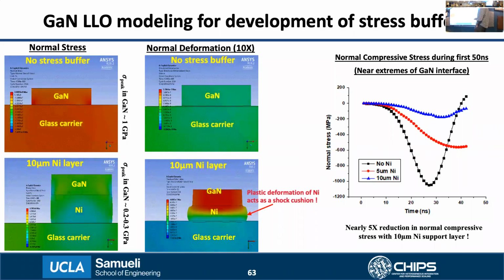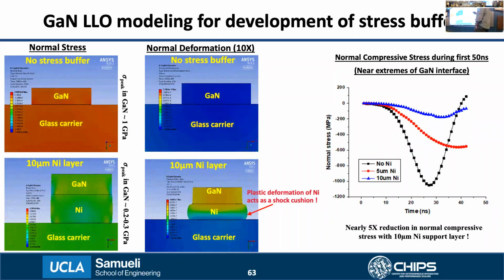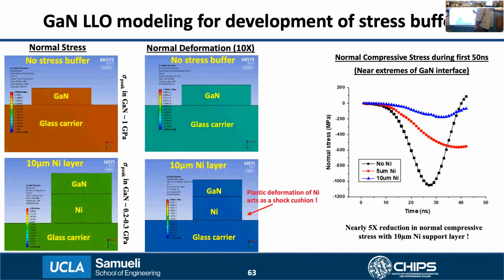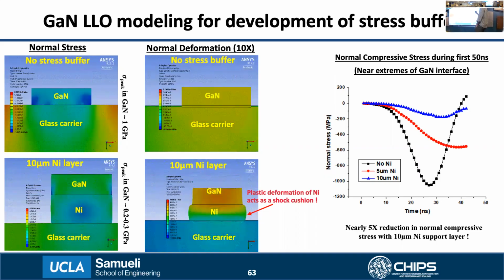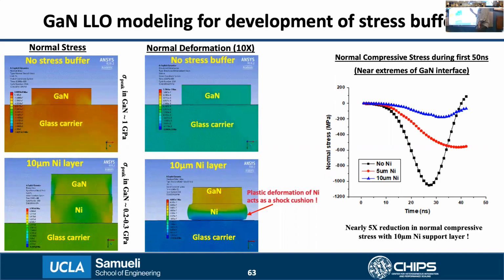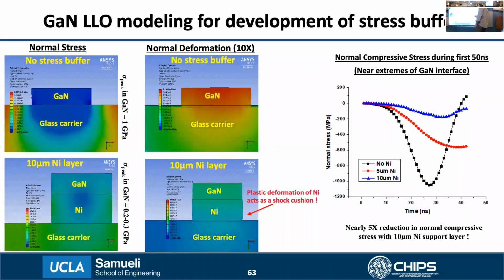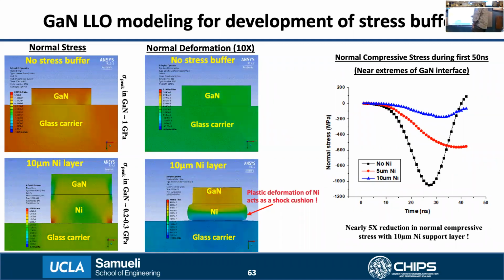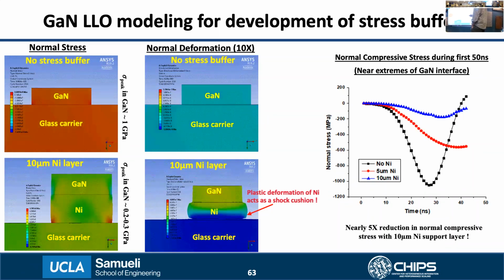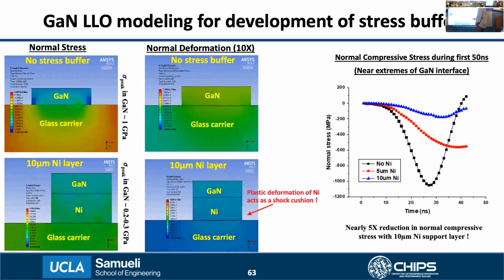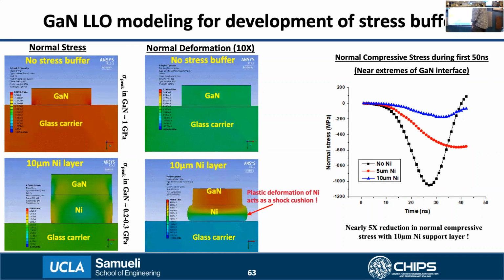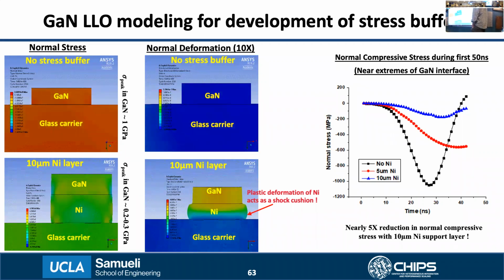So here you see the full results of the ANSYS mechanical simulations of the GaN LLO process, which takes into account both the thermomechanical shock wave as well as the nitrogen pressure shock wave. On the left, the animations plot the normal stresses in the cross section, and on the right, it plots the normal deformation multiplied by a factor of 10.